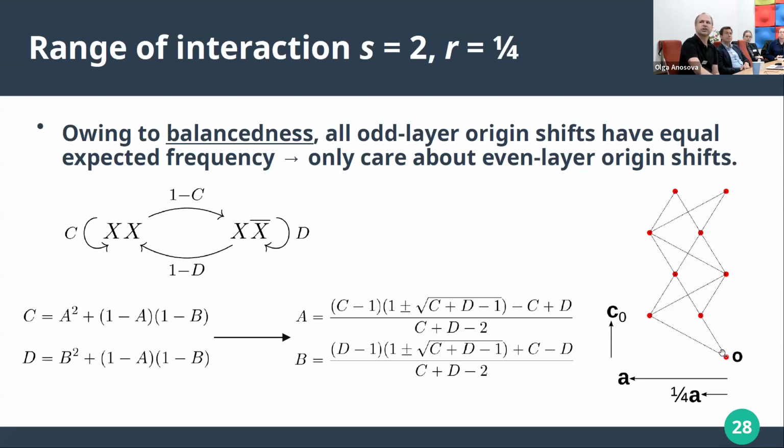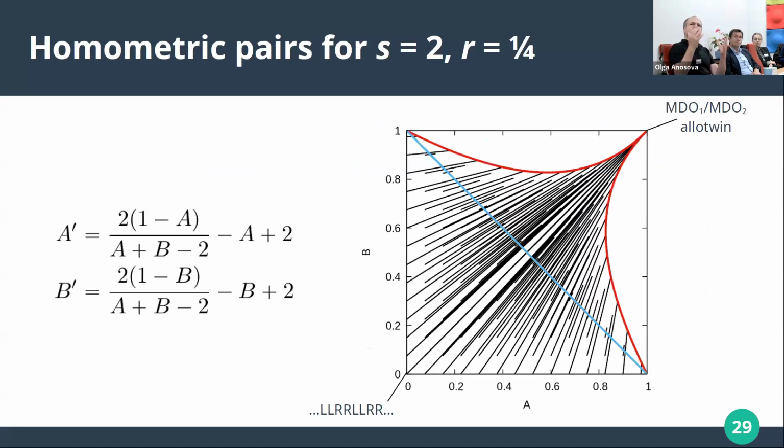So you can ignore them. So we only have to look at every second step, and we get a simpler Markov chain with parameters C and D. And when we back calculate, we see that we have lots of pairs that give the same diffraction pattern. You see, I've connected these pairs by a line, a line segment, to be more precise.